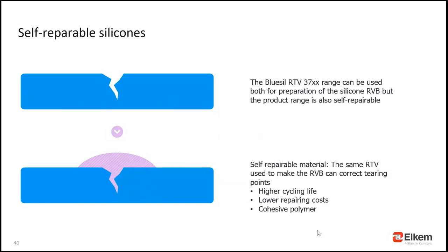This means that in order to fix a torn area in a long-used mold, the same silicone used in the RVB production is able to adhere to the cured surface and reach up to 65% of its original tensile strength. No repairing materials are necessary here. In the long term, more resistant silicone with the ability to be repaired means a greener and less wasteful process.